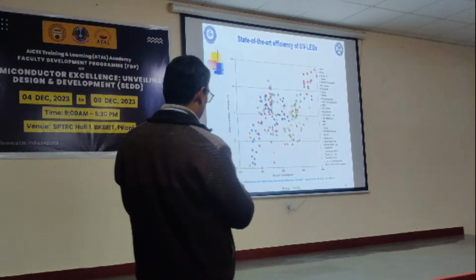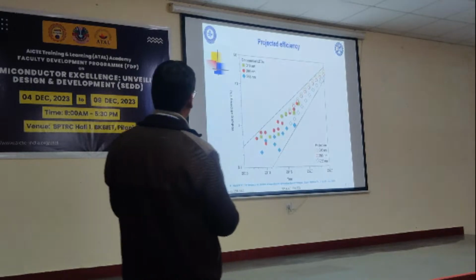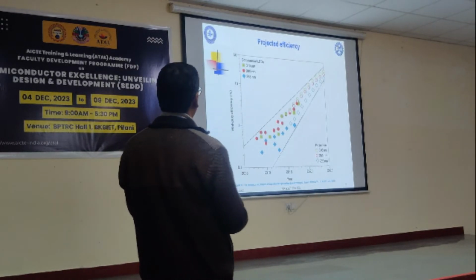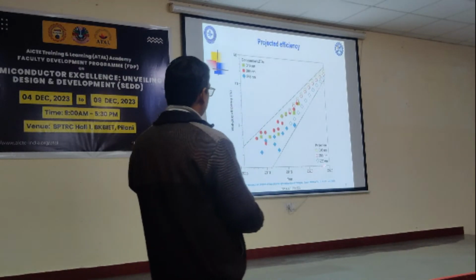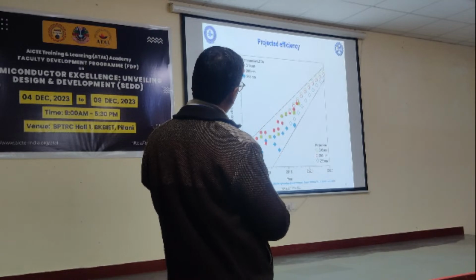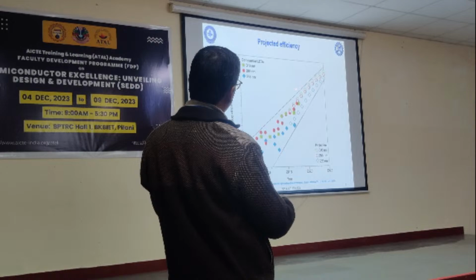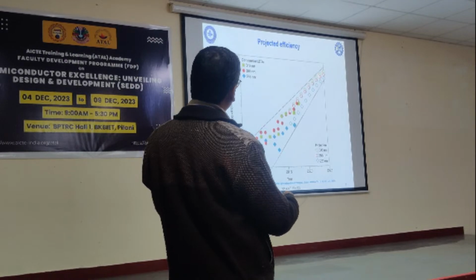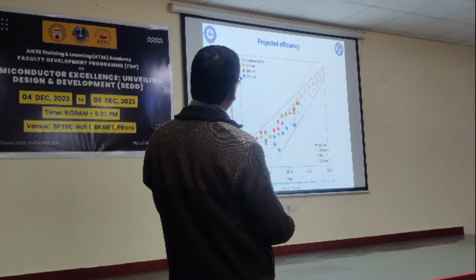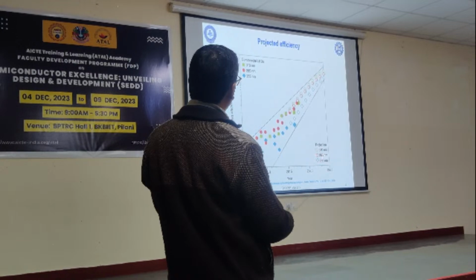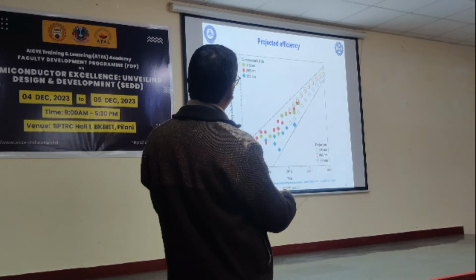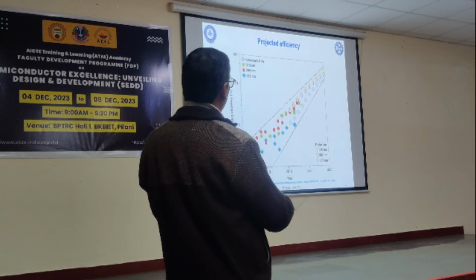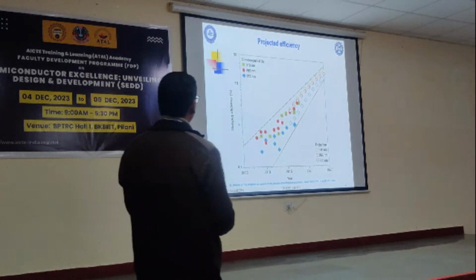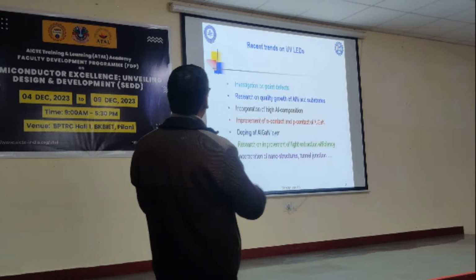So you see that it is within 10% external quantum efficiency. We are projecting that the efficiency will obviously improve with time. This is what we have achieved in real time, but we are progressing, and the efficiency will reach around 20% by the year 2025. You see that this is 310, 285, 360, 265. As the wavelength goes lower, the efficiency is low, but we are trying to converge with time. There are various ways of working in the area of UV LEDs.